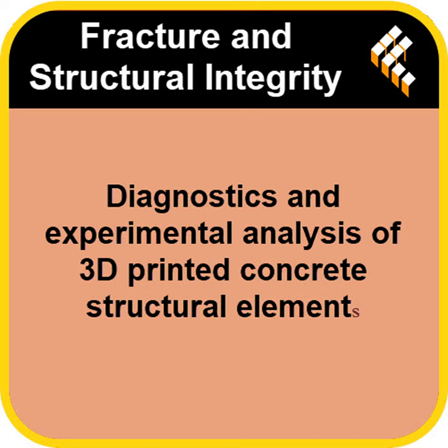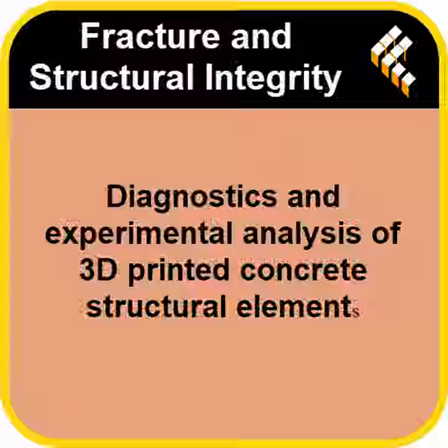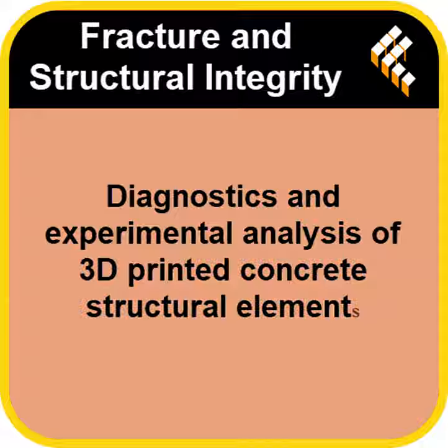But the real star of non-destructive testing for concrete is usually ultrasonics, right? UPV. Can a sound wave find a bad bond? This study confirmed it absolutely can. UPV showed an excellent correlation with both strength and its elastic modulus. How did it work? Well, when they measured the pulse velocity across the print layers, they saw an average speed reduction of about 400 meters per second. So about a 7% drop.